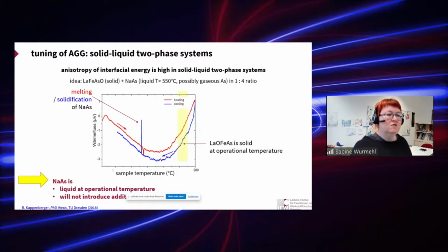So we used additional sodium arsenide to increase this interfacial energy. But please let me stress here that this is not a flux growth. Flux growth always implies that you dissolve your target material and then crystallize it at a specific temperature. This is not the case here.